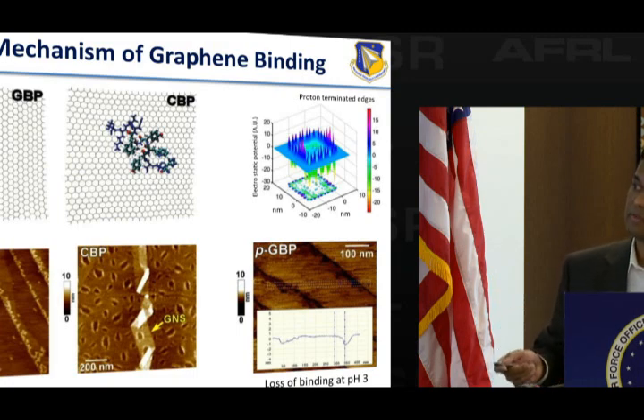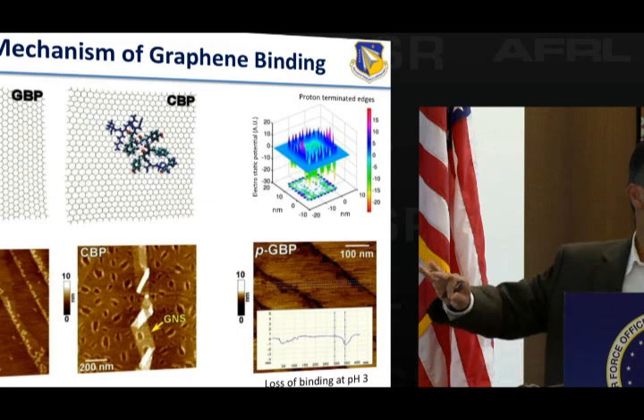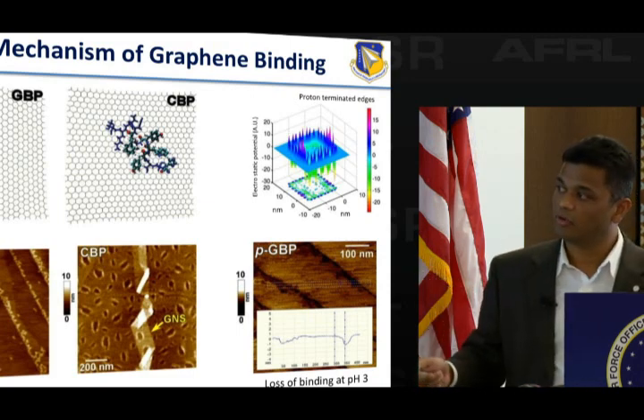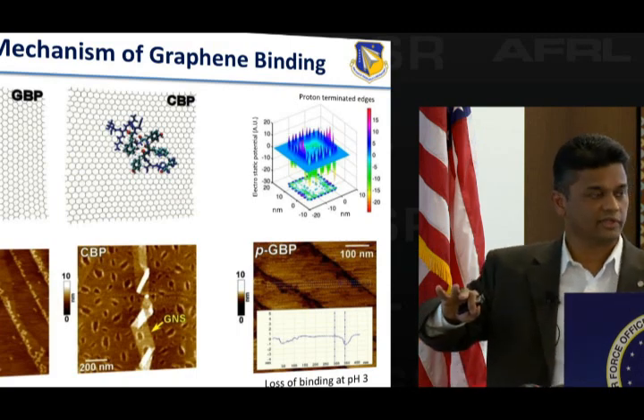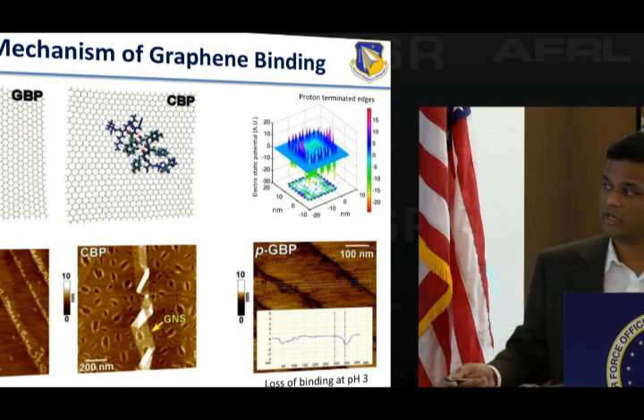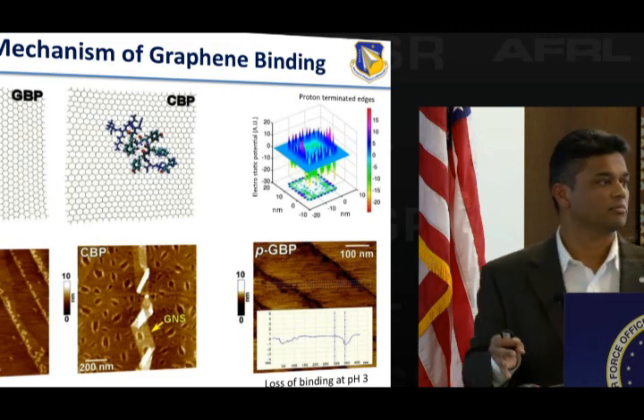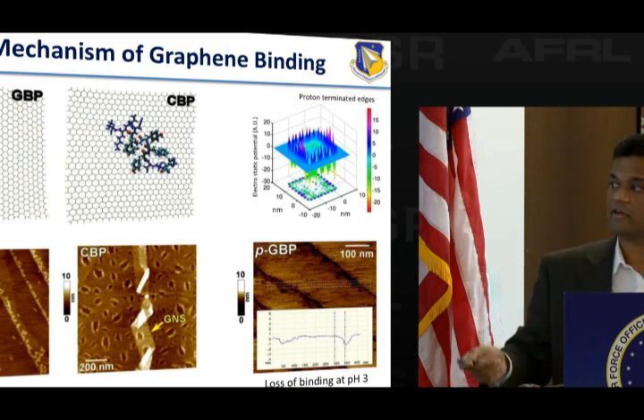And you can see this peptide, for example, these are the edges of that HOPG sheet. And you can see the peptide actually assembles and aggregates at that edge. Okay. It does not coat the whole surface. Whereas this peptide coats the whole surface, it forms a monolayer, but because there's water that's lost during the evaporation, it leaves this sort of herringbone structure behind. Okay, that is just an artifact of the drying process.